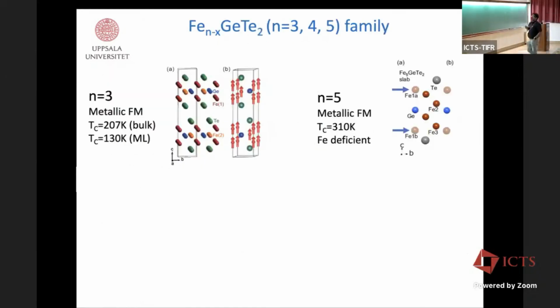Coming to the systems, Fe N-X germanium telluride, N can be 3, 4, and 5. Minus X because people usually observe there are some iron vacancies always present in the system. And this is a known fact, but still this has not been systematically studied as to how the properties actually change with the concentration of iron. This is something one needs to do.